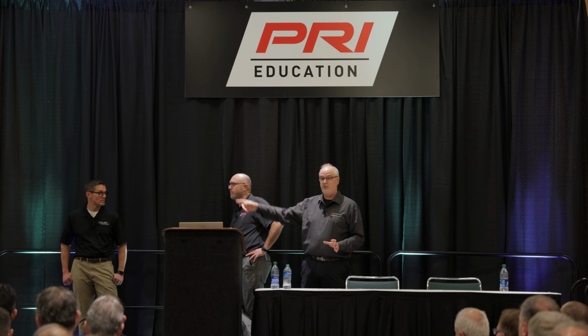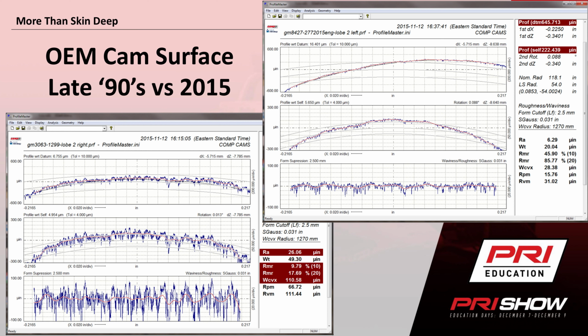You can see that this is GM stuff. This is a first generation LS1 on the very left, and then a modern LT on the right. And you can see that GM has gone in there and put significant crown in it. Part of the reason they run crown is, if you take an old 300,000 mile Chevy apart and look on the base circle, you'll see that the wear pattern's really narrow, then it gets wide in the flank, then narrow, and then a little wider on the nose. Well, that's because they put a ton of crown in it.